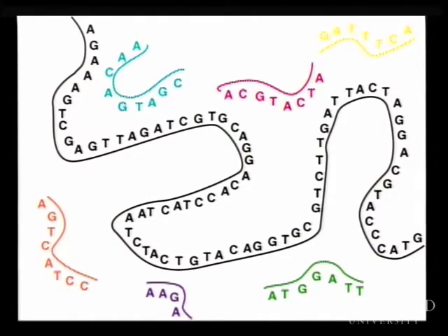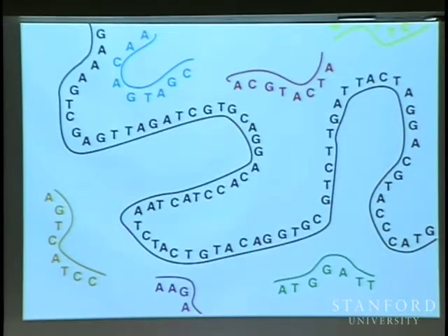What I mean by making them, this maybe should answer your question, is there's a machine about the size of a photocopier called a DNA synthesizer, and it's got a little bottle of A, a bottle of C, G, and T on it, and you type in A, G, C, T, and it has a bunch of tubes and piping, and it washes the chemical constituents, A, C, G, and T, over a little glass column, and they bind in order, and you create the sequence of interest, and then you add another chemical, and it cleaves it off that column, and you are left with a little tube that's exactly the sequence you want.